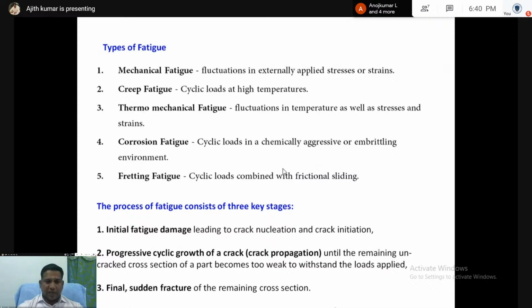So three stages are there in fatigue analysis: initial fatigue damage, progressive cyclic growth, and final sudden fracture. The first one is initial fatigue damage, leading to crack nucleation and crack initiation. That is initial fatigue damage. Then progressive cyclic growth of the crack, until the remaining uncracked cross-section of the part becomes too weak to withstand the applied load. And then the final stage is sudden fracture of the remaining cross-section. That is final sudden fracture.